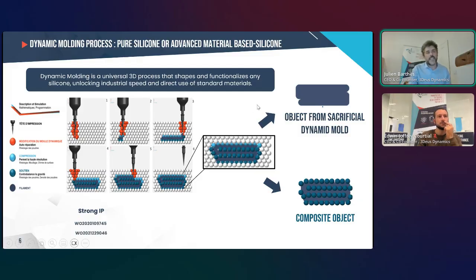And at the end, you can get two different kinds of objects. As the powder can mix with the silicone, you can either keep the powder inside to get a composite object, or you can decide to remove the powder that mixed to get pure silicone material. In that webinar, we will focus more on how we get composite objects, because the process is compatible with a large range of industrial powders, so you can tune the properties of the composite the way you want.